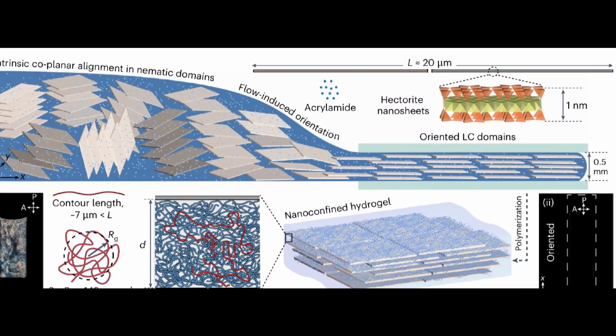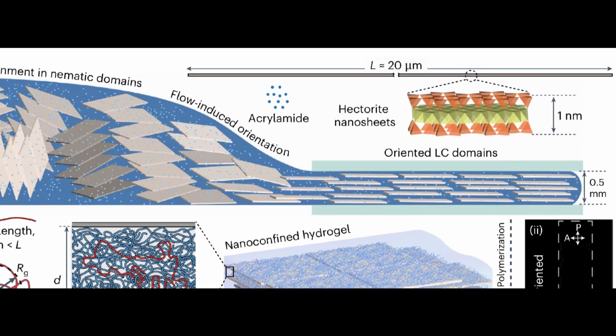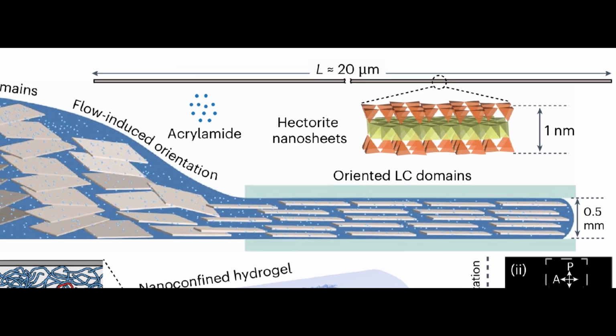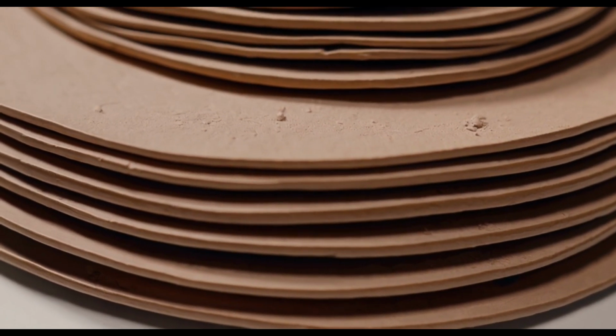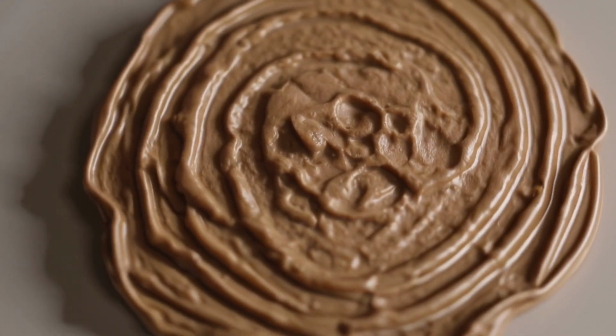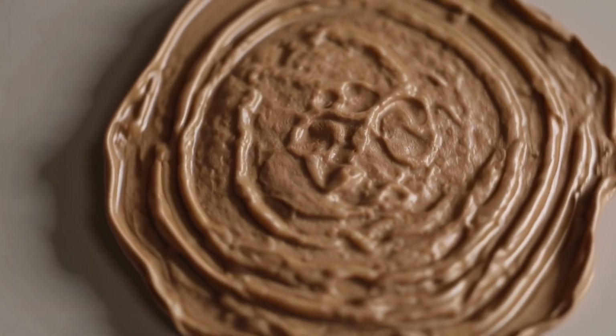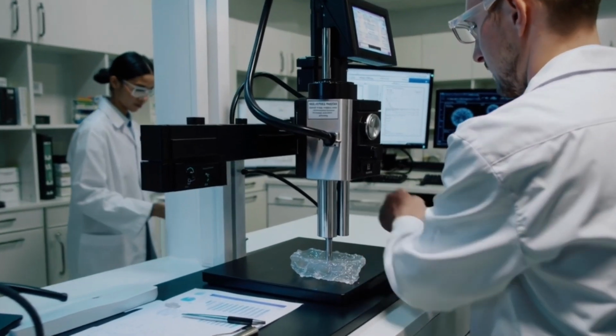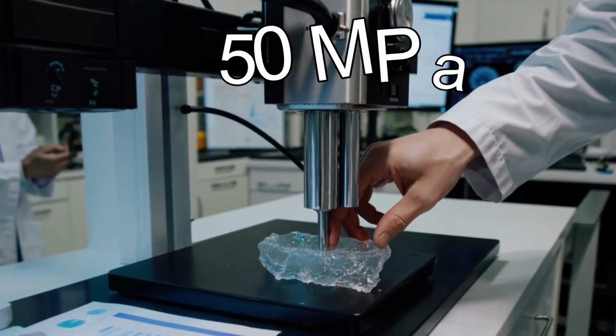That's what happened when they exfoliated hectorite clay into 1 nanometer thick, 20 micrometer wide nanosheets and sheared them into aligned pancake-like layers, forming a co-planar scaffold for acrylamide chains to grow and entangle. Inside this nanoconfinement, the hydrogel's Young's modulus jumps to 50 megapascals, rivaling soft plastics and rubber.